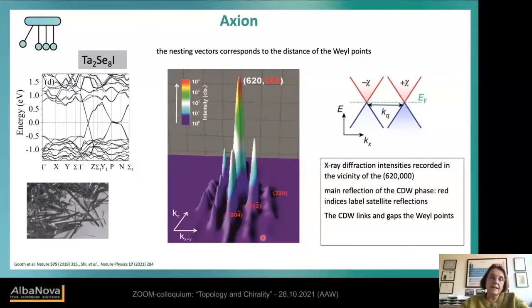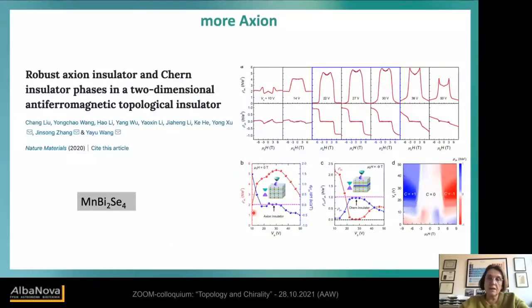Yeah, and very important was also that the prediction was that the charge density wave should scale with the nesting vector between the Weyl points. And this is exactly what was then found in synchrotron-based XRD. So we have the superstructure reflection peaks beside the main reflection, which is related exactly to the vector between the two Weyl points. Okay, so meanwhile, also in magnetic materials, like this manganese bismuth selenide in monolayers, which is a magnetic topological insulator.